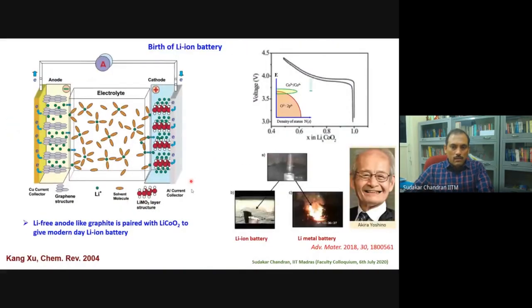Of course, until Akira Yoshino came up with a suitable anode, the birth of the lithium-ion battery was not realized. So he used some carbon-based material, which also had a layered structure, and lithium can easily intercalate between the layers. And so that gave a lithium-free anode, the graphitic anode, which was suitable for lithium cobalt oxide as cathode to begin with. Therefore, your batteries could be assembled, and Akira Yoshino showed that if you make the battery using lithium metal as the anode, if you hammer the batteries, they catch fire very easily, whereas the lithium-ion batteries made with graphite do not catch fire. And this instant is considered as the birth of lithium-ion batteries. Of course, the Sony company went on to make the first commercial batteries using this material.